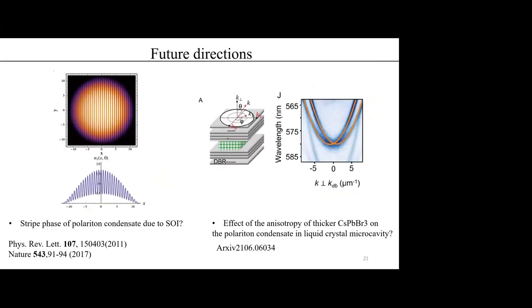Okay, in the future, we are planning to study whether the stripe phase of the polariton condensate can be observed or not. In the cold atom condensate, the stripe phase has been predicted and measured by using Raman lasers. Now the problem for our microcavity is that the condensed polaritons seem to be localized in a small region of around 5 micrometers. Our next step is to improve the quality of the perovskite microplates.